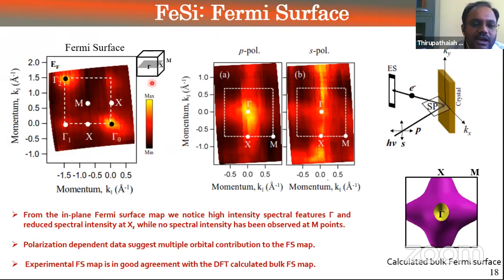So this is the Fermi surface map, an in-plane Fermi surface map in the gamma X M plane. This is the first Brillouin zone, let's say, the gamma point where you have finite spectral intensity. And then we moved quite far to reach another Brillouin zone. I won't say second, in the sense that it's in the same plane. Actually, it moves up a bit, either up or down in ARPES. And this is another gamma point with a different Kz value, and again, this is another gamma point with a different Kz value. So in ARPES, when you go a bit far away from normal emission, you actually reach different Kz planes. Then we zoomed in on this area and remeasured the Fermi surface.